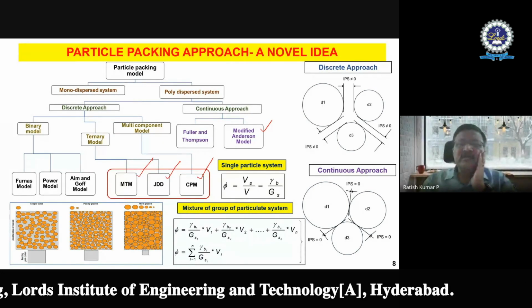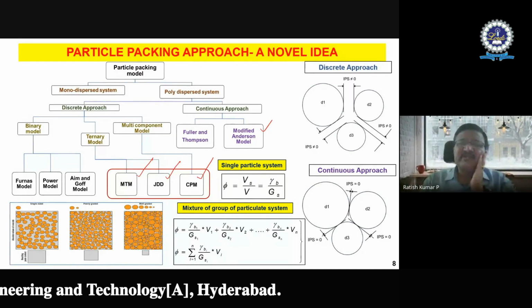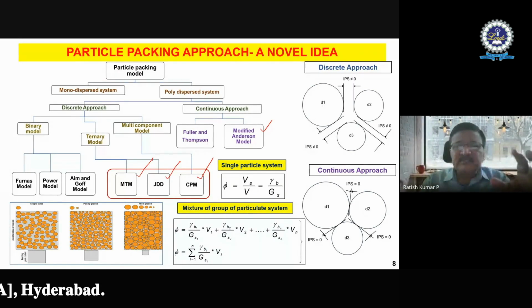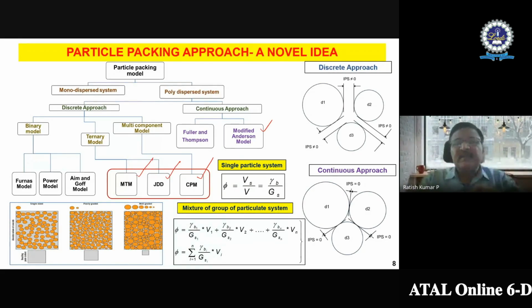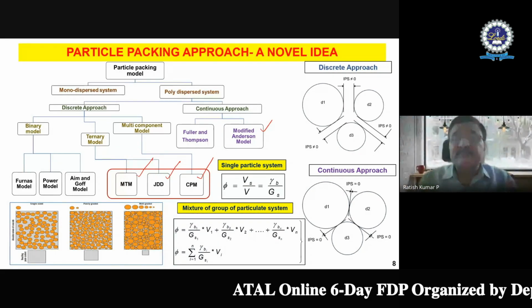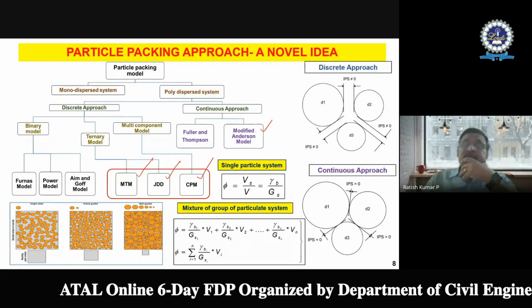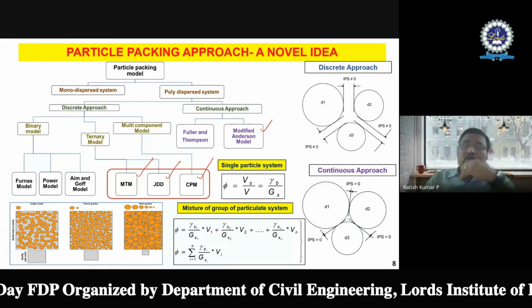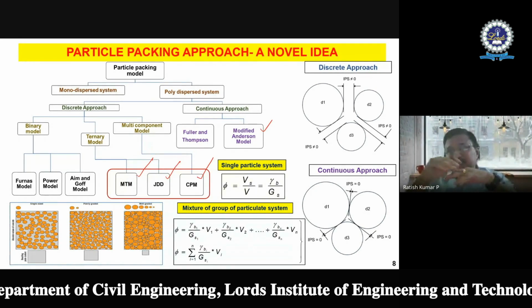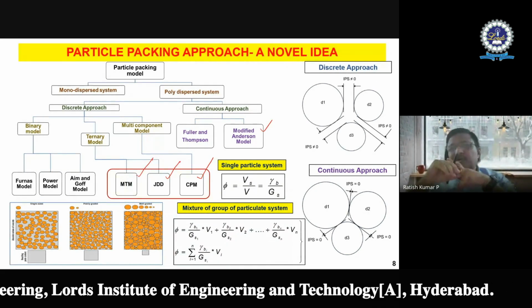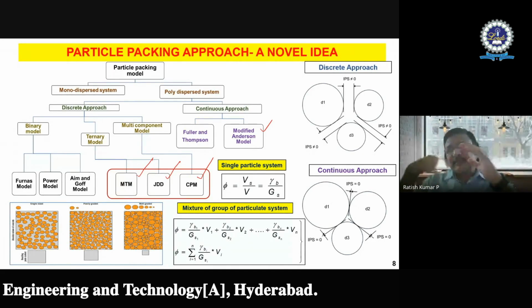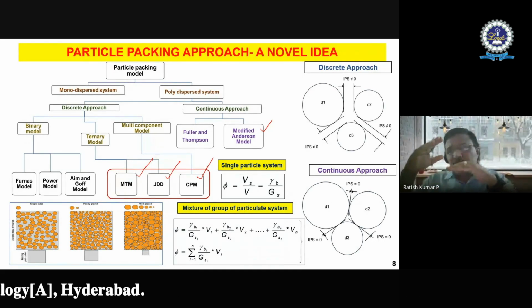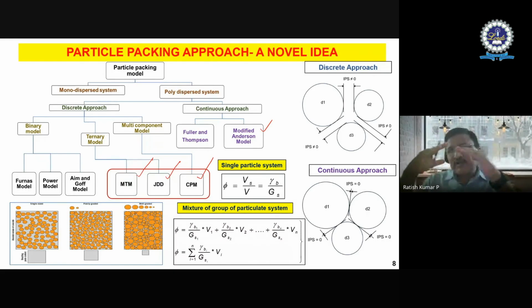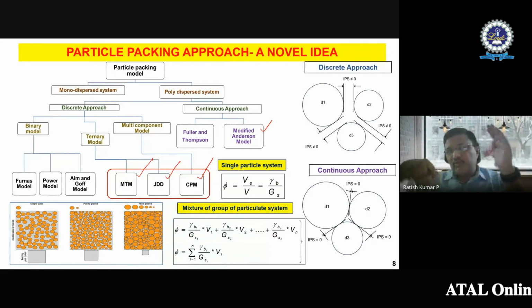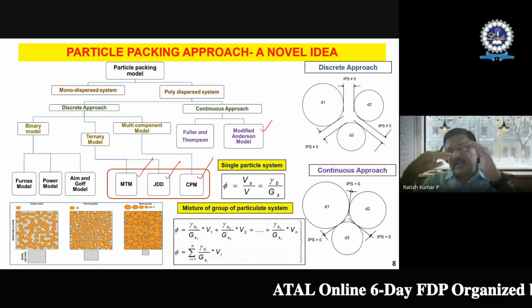The concept is only about achieving maximum density by packing these aggregates in such a way that you get the minimum amount of space to be filled up with the cement paste, of course satisfying the minimum cement content requirement. The reason this propped up in our mind is IS 383, table 5, where we have the different sieve sizes. And you can notice that there is a large gap between 40 and 20, 20 and 10 directly, and 10 and 4.75. So we thought, is it really possible to fill up?